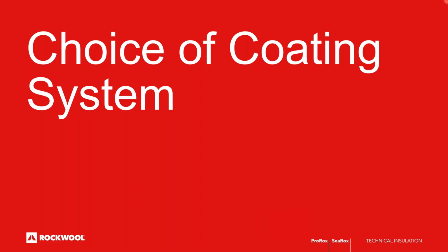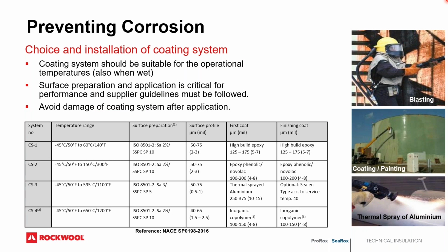So then you've got choice of coating. Now, this particular chart you see in front of you references the NACE SP0198 2016. And when I speak of coatings, I'm talking about an actual coating that goes on the surface of the pipe, steel or tank, as you see in the pictures, that allows for protection against sitting moisture on the surface. This puts a barrier between sitting moisture and the actual metallic surface.